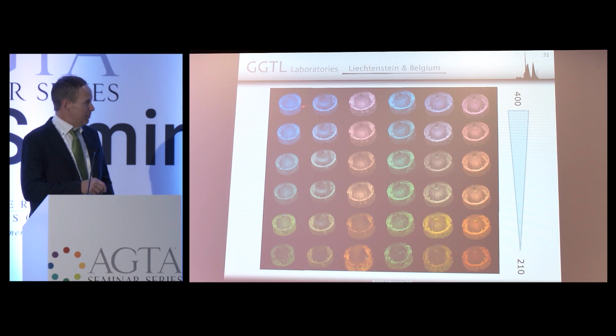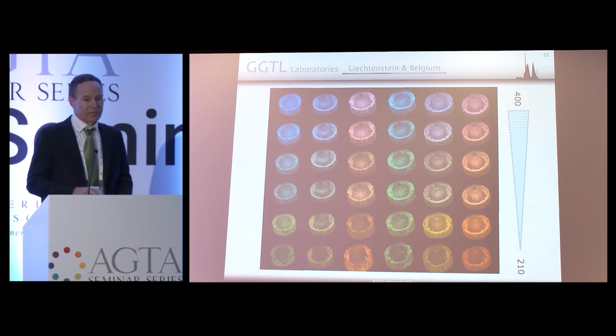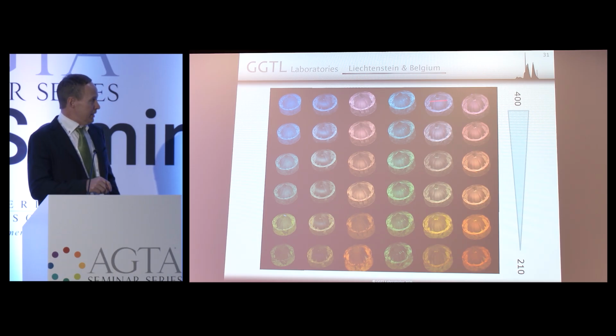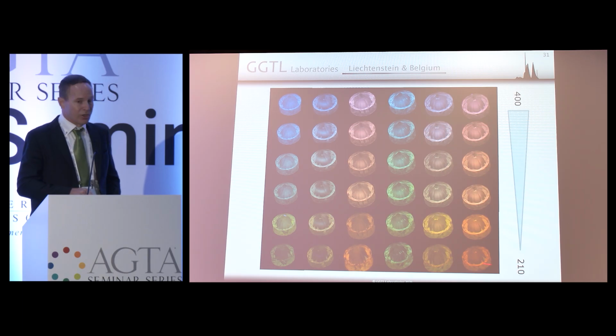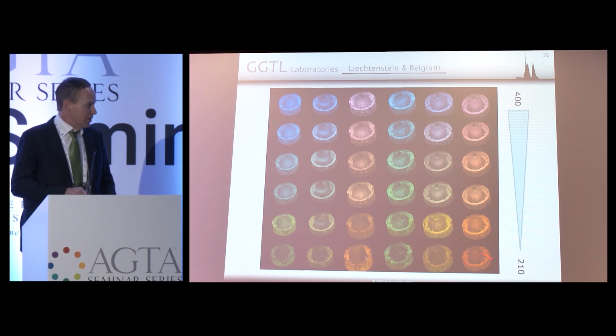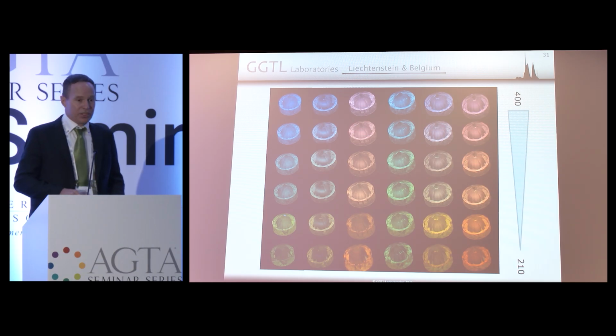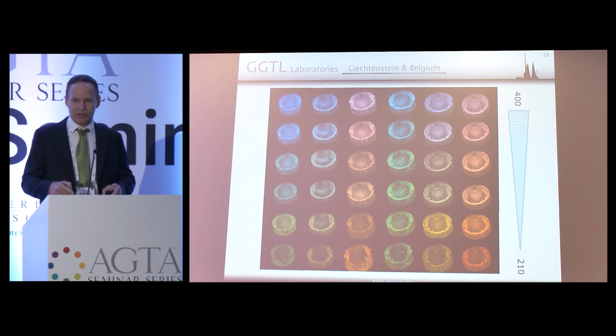But anyways, you can be anywhere from blue through violet, through purple, through greenish blue, in long wave, in HPHT treated material, and every time when you go towards short wave and deep UV, you get into more of a yellow to green to orange response, which is unlike anything you would see in a natural diamond. And that's how you can distinguish them easily.